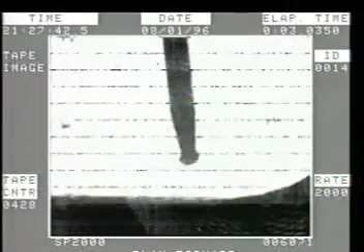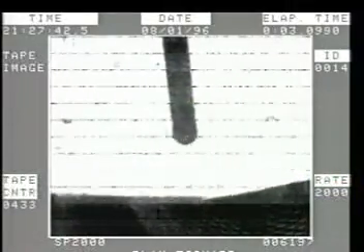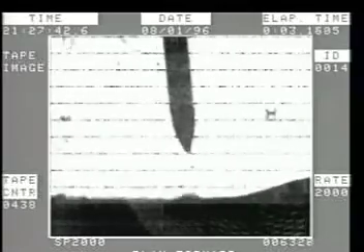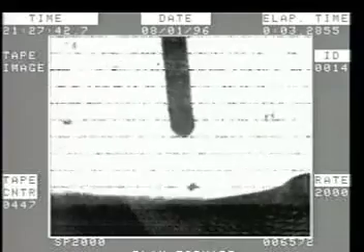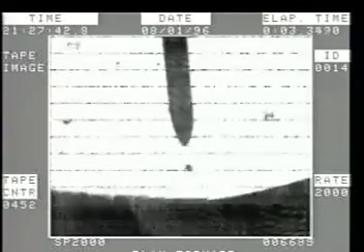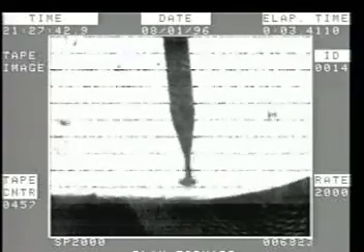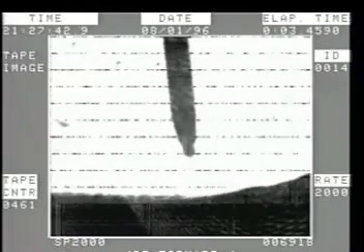Let's look at the pulse process at a higher wire feed speed. This is not pure pulse welding, rather an intermittent spray arc welding. The PowerWave power source has waveform control technology. It provides a very fast front edge on the pulse, transferring the droplets quickly. The back edge of the pulse falls at a controlled rate to add the heat input needed to wet the droplet into the puddle. Pulse spray is stable at a wide range of wire feed speeds.